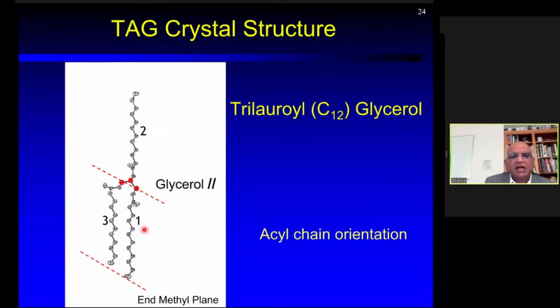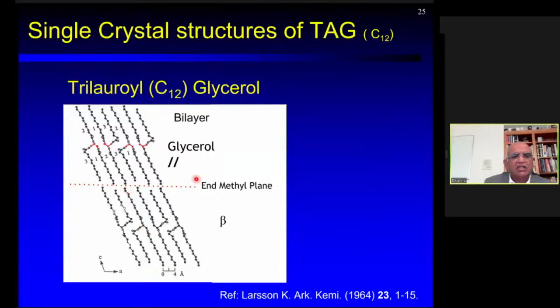So in its single crystal structure, the same triacylglycerol is shown here, projected along the b-axis. Here is the triacylglycerol, 1 and 3 chains together, 2 going up, and this triacylglycerol, 1 and 3 chains packed together, 2 going down. So they pack in a stacked chairs in a bilayer mode, as is shown here with 2 chain length structures, with the glycerol being parallel to the methyl plane.